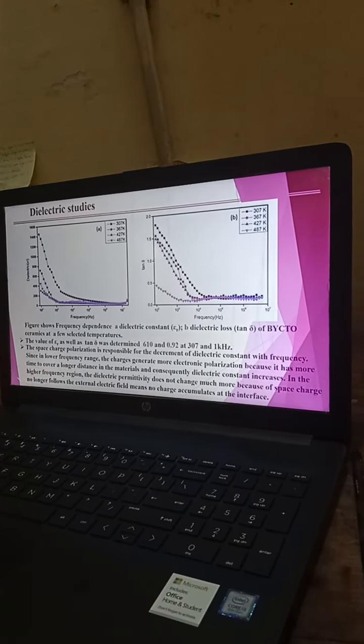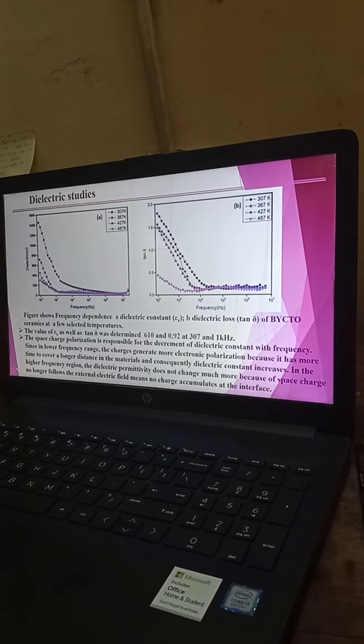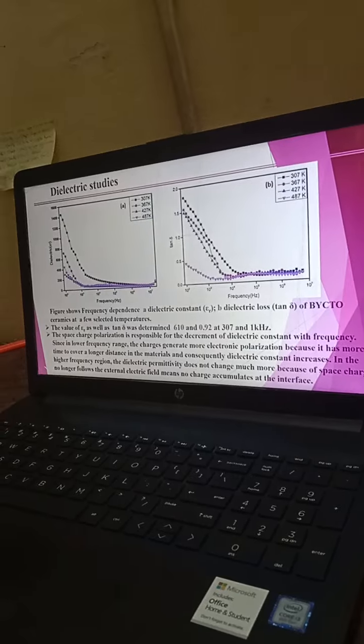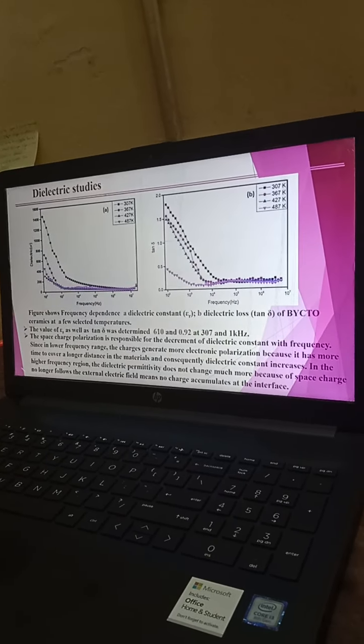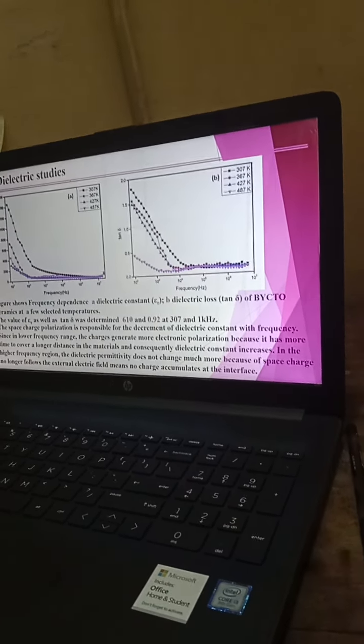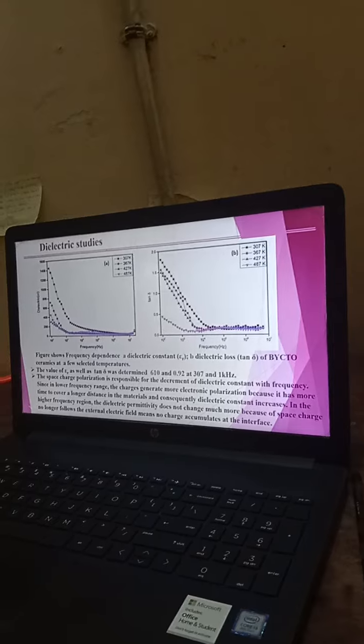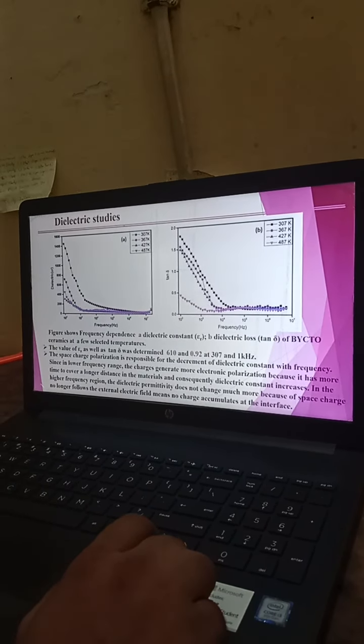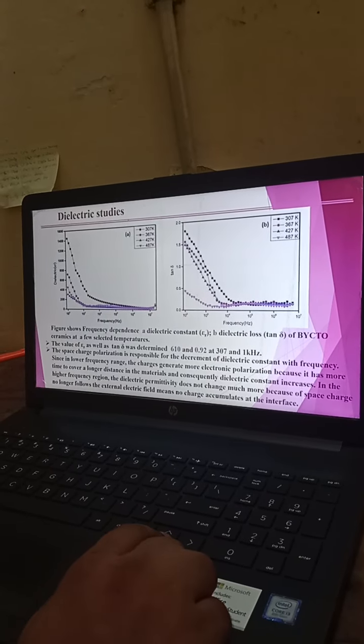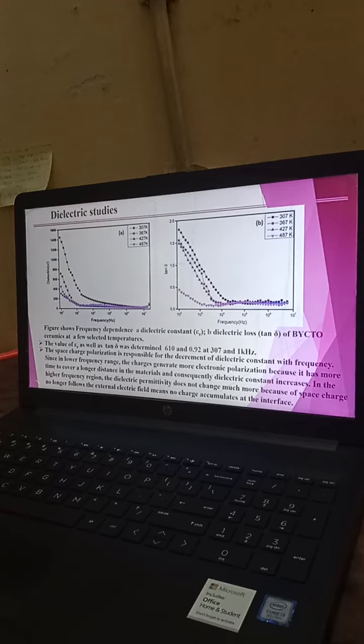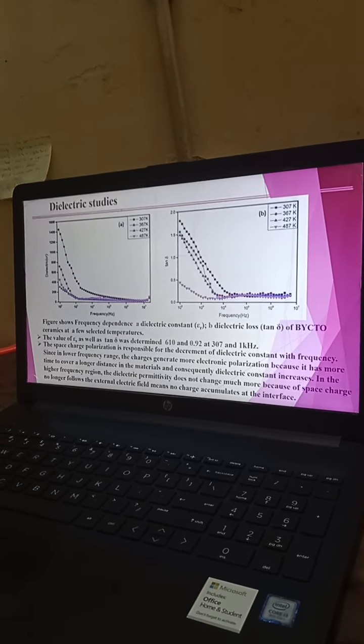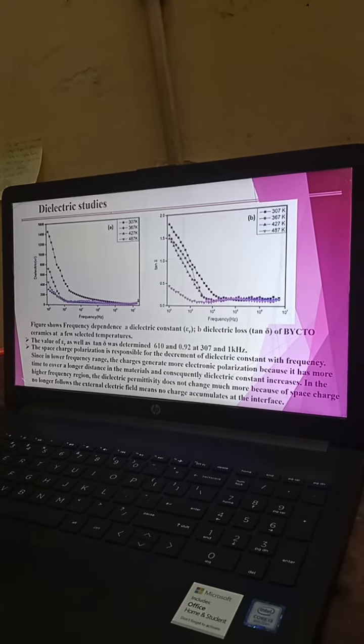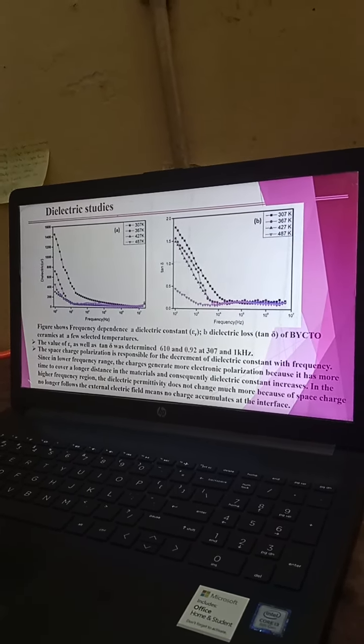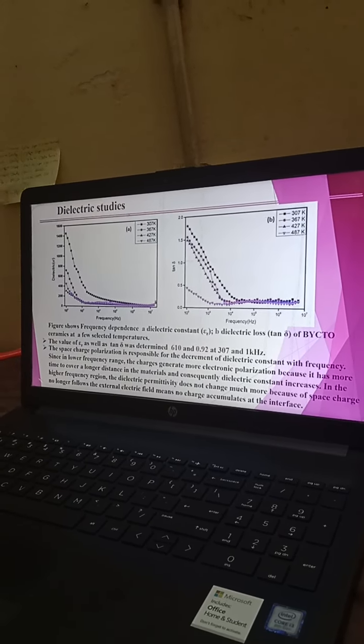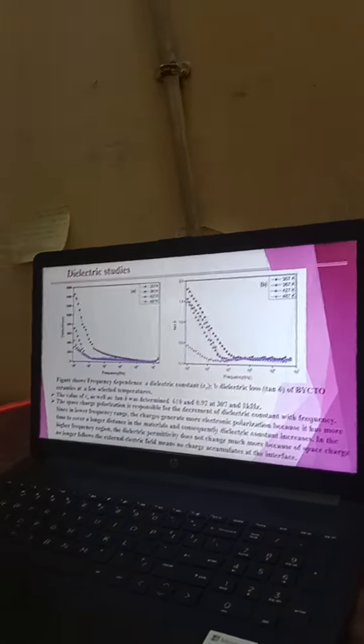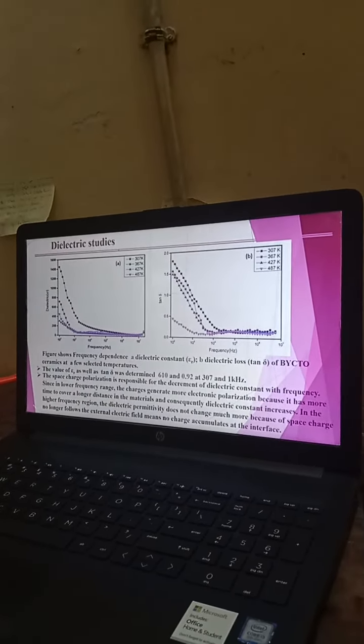Since in the lower frequency region the charge generates more electronic polarization because it has more time to cover long distances in the material, consequently the dielectric constant increases. But in the higher frequency region the dielectric permittivity doesn't change much because of space charge polarization. Space charge no longer follows the external electric field, meaning no charge is accumulated at the interface of the grain and grain boundaries. The dielectric constant as well as dielectric loss was determined to be 610 and 0.92 at 307 Kelvin and 1 kilohertz.